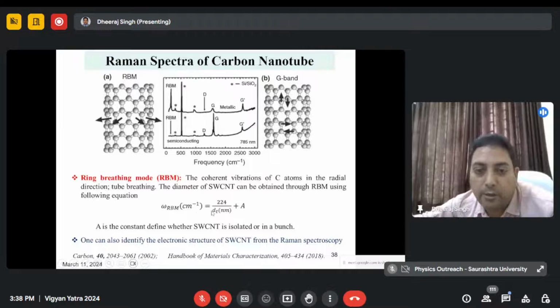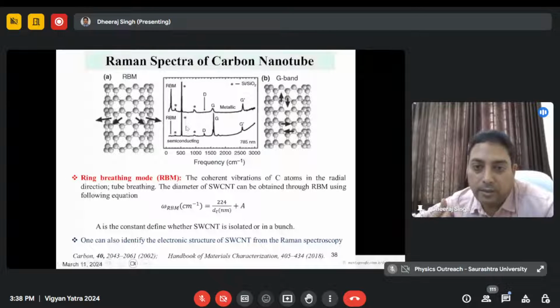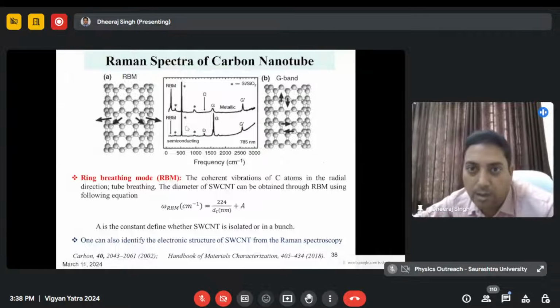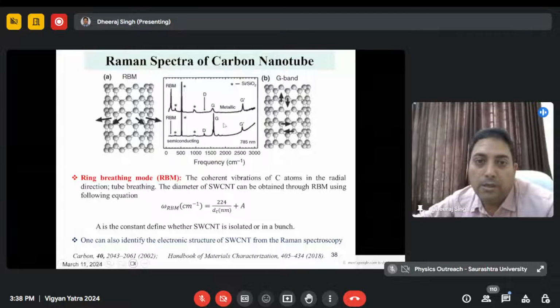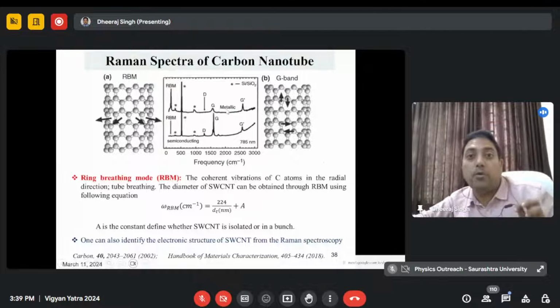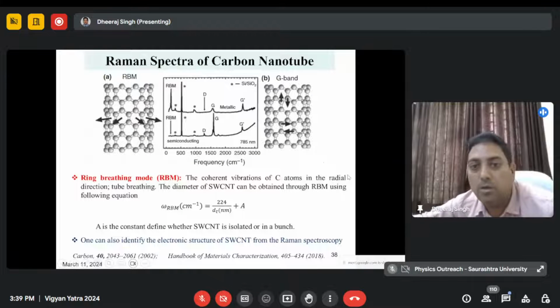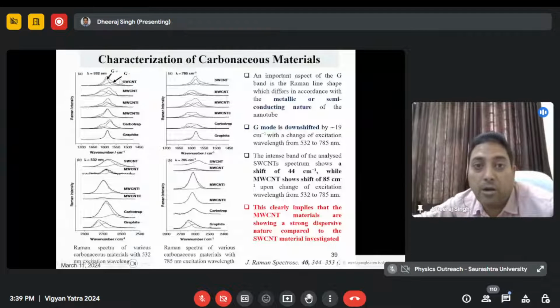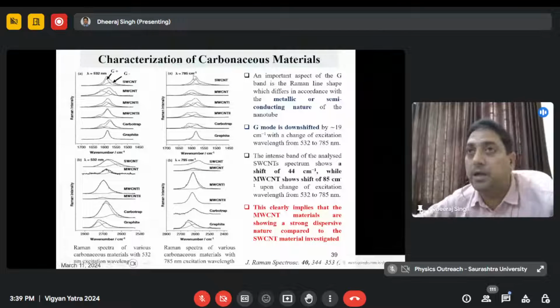And we can calculate by this equation, 224 upon d_t plus A. By this vibration, you can calculate whether it is a single wall carbon nanotube or a multi-wall carbon nanotube. You can also find out whether it is a metallic component or a semiconducting component. Characteristics like metallic or semiconductor, or multi-wall or single wall nanotube, can also be characterized by Raman. Also there are certain changes in the wavelength of the laser light.